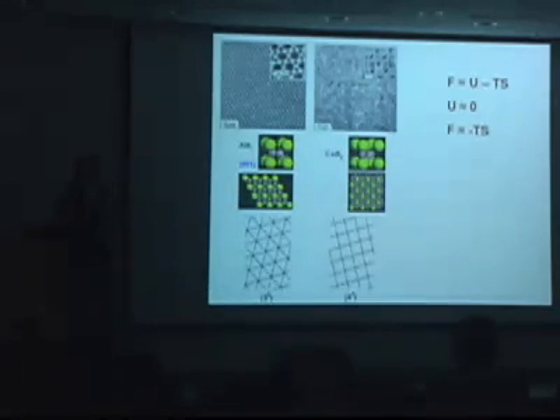Okay, now we can have the same particles taken into two different packing lattices. One lattice is isostructural with aluminum boride, and in the 001 projection of this lattice, we can describe it as triangular packing. On the other side, we can pack the same particles into a superlattice isostructural with calcium hexaboride. It's a pretty remarkable structure because you have a simple cubic arrangement of large particles, and in the center of each cube you have a small octahedron of 6 small particles. So, don't ask me how this assembles, how it was possible to spontaneously assemble such a complex structure, but it forms.